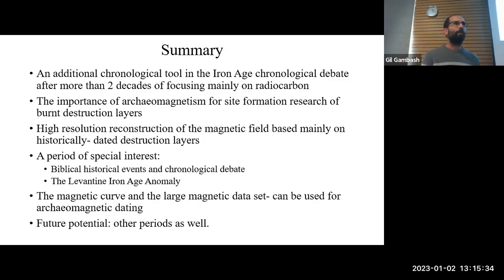I showed why the site formation is so important, also in itself, but also for the dating, to understand when the magnetic data comes from. And we have here a real high resolution reconstruction of the magnetic field because we use the very good dating of archaeological materials, based on historical sources, the chronological anchors, and the radiocarbon, as I showed in the case of Megiddo. So the good combination of history, archaeology, radiocarbon and the magnetic field resulted in a brand new dating method.